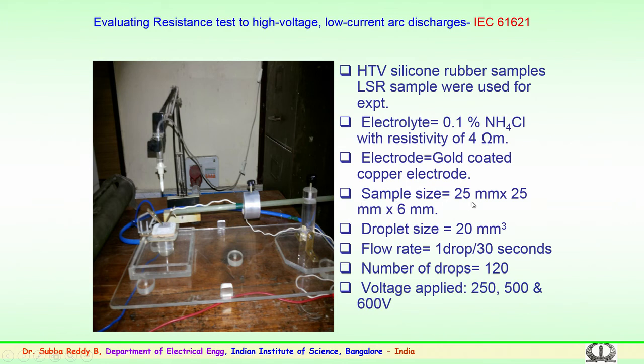The sample size was 25 mm by 25 mm by 6 mm in thickness. The droplet size was 20 mm cube, a very small droplet has to fall in between the electrodes. The flow rate of the droplet is 1 drop for 30 seconds. So, you have 2 drops in a minute falling on the sample during the electrical stress. The voltage applied between the electrodes was initially 250 volts, then 500, then 600 volts. So, the voltage levels were changed, and the droplets were 120 in number.